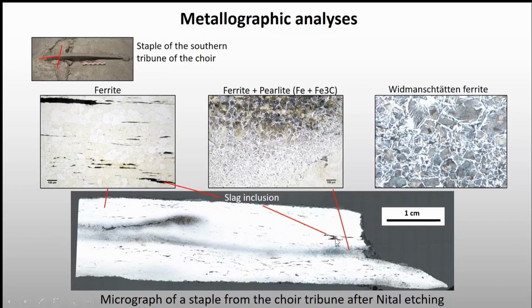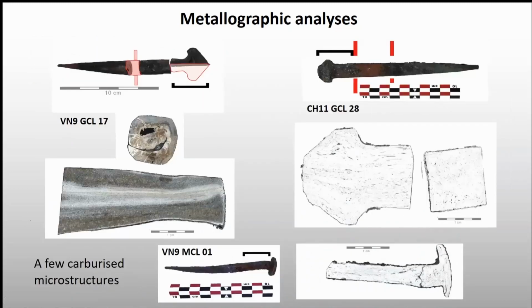They are impurities that are principally made of iron silicates, which come from the ore and which are the unreduced part of the ore. Most of it is expelled from the furnace, but as iron was not produced in a liquid state before the end of the 19th century, some of these slag remain entrapped and form slag inclusions in the matrix. So it has an importance for the quality and the mechanical properties of the iron. We'll see that later, but it's perfectly normal for ancient iron such as this one.